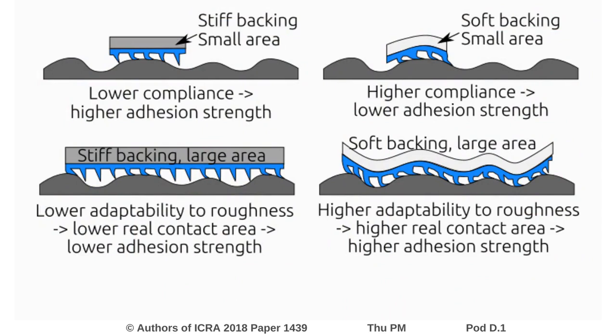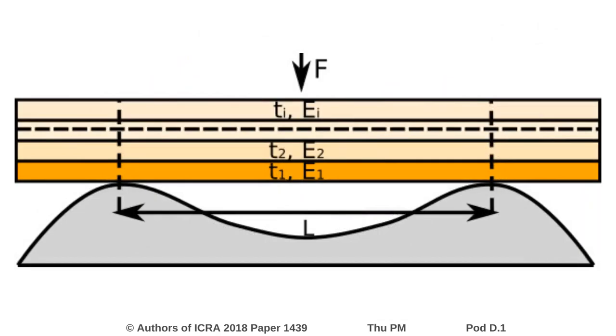However, on rough surfaces, the contact area depends on the compliance of the structure and will increase with increasing compliance. This is even more significant in the presence of an electrostatic preload. Overall bending compliance can be increased by increasing the adhesive's area and decreasing composite stiffness.